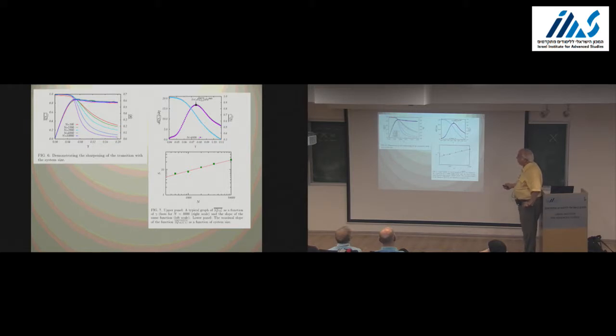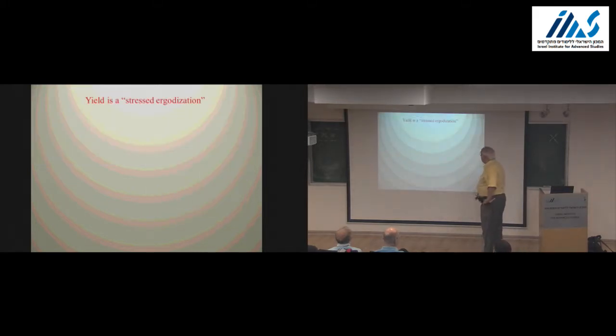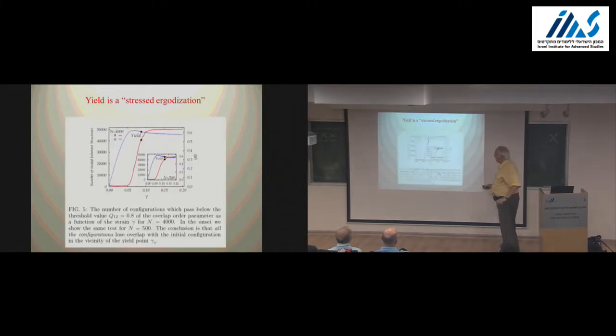You want to quantify it. So you look at the maximum slope. You look at the slope, you pick the thing at its maximum, for example on this curve, this is the slope, you find the maximum slope, and you now plot the maximal slopes as a function of the system size, and you have a very nice parallel, as you expect in a real transition, like in the first order transition. So yield is something like a stressed ergodization, in the sense that the huge vista is opening up at the yield, which you didn't have as long as you were in the elastic regime.